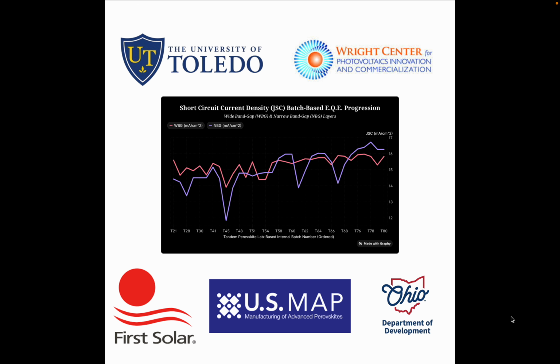And so what this really tells us, and there's a hint here for the future, is not only that we can do well in our cells, and that some of this research, the space-based research, is kind of at the top of the field and ready to be published, but really it shows us that our cells could be kept up. So all of the cells in the solar panels you would see in space are this silicon material, radiation damaged, heavier, and with perovskites having enough retention of their efficiency, right, with minimized degradation like we've seen, we're actually shifting into a new realm where we might be able to commercialize these devices and really put these new and improved energy systems in space.